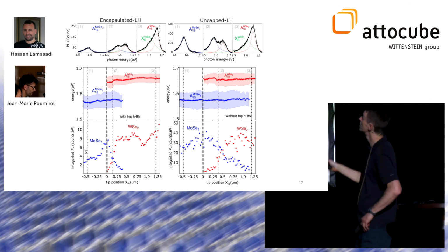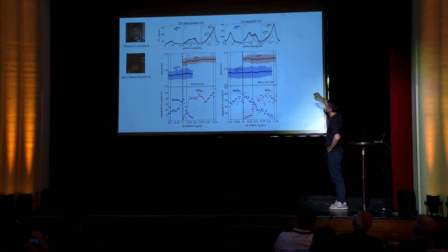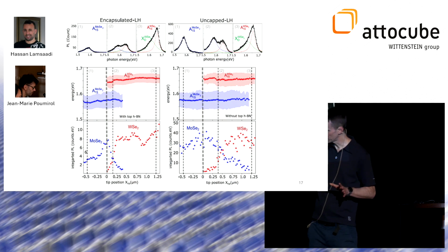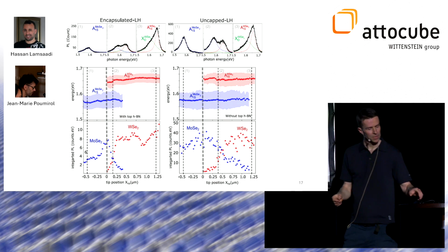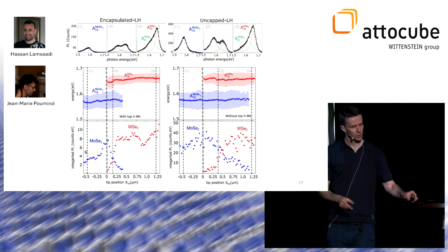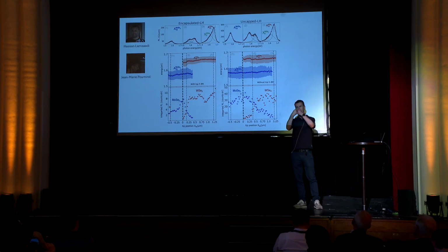Surprisingly for us, the one that didn't have hBN on top allowed the excitons to travel further. We do not have any super explanation for this. There has been a paper from Alexei Chernikov, Ermin Malic, and Misha Glazov, where they looked at scattering mechanisms. You can maybe imagine that in this slightly rougher sample, you have more of this kind of Auger scattering. With this, you do create excitons with incredibly high energy, and they then have the potential of going further.